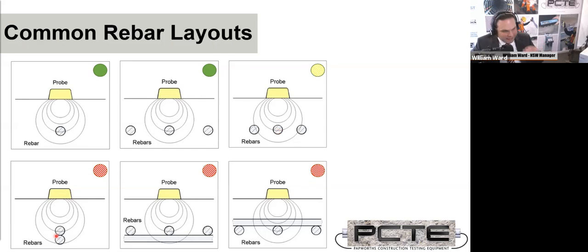If you have lapped reinforcing bars, you will read an artificially thin cover depth. This is quite important. That's why when you survey a wall or a floor or a structure, there will always be regions where it becomes more difficult to locate the position of bars with the cover meter, and the bars all seem like they're much closer to the surface than everywhere else. What's likely happening is this is where one layer of reinforcing bars, say vertical bars, are overlapping a second layer of reinforcing bars. So you've got additional metal.